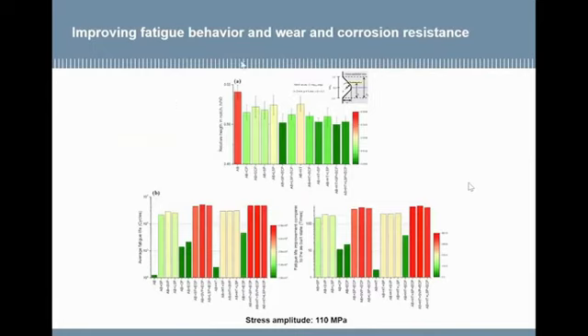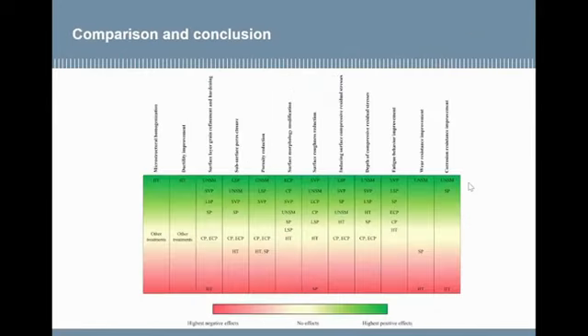Here you can see the position of the fracture surface that has been quantified with this relative height in notch parameter. And as you can see, for the as-built and the heat-treated samples, they are much higher compared to the notch root, and they are getting much closer to this 0.5 value that is the position of the notch root. And then in terms of the fatigue life, again, we have a considerable fatigue life improvement for rotating bending fatigue tests that were performed after the post-treatment.